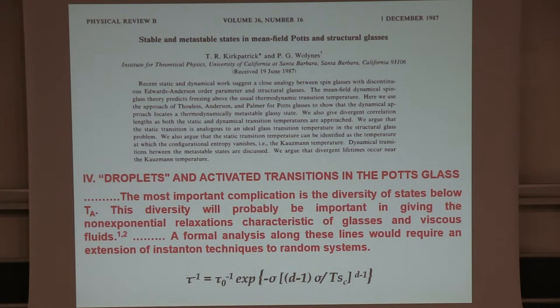They also found, weirdly, that there were two transitions, but that fit nicely with the picture of Singh-Stoessel-Wolynes, that there's one transition of kinetic stability and another transition of thermodynamic stability. By the way, that first transition really wasn't noticed in the calculations of Gross, Kanter, and Sompolinsky because you have to divide by zero. And you know, David Gross is a little bit too professional to divide by zero without mentioning it. But Ted was a little more bold.